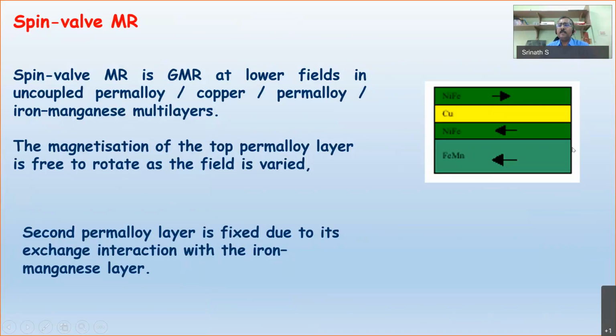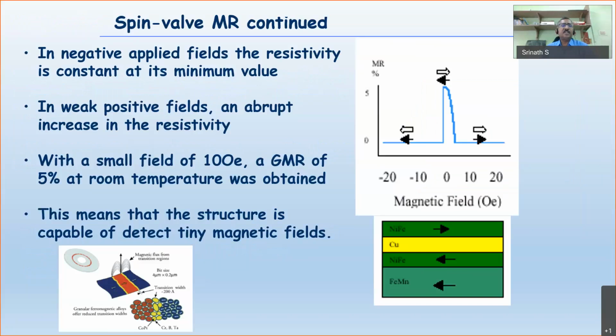So people have done, like, nickel iron and nickel iron. These are two ferromagnetic layers separated by a copper non-magnetic spacer layer. And one of the ferromagnetic layers is coupled with an antiferromagnet, iron manganese. So you can pin this layer, and the other can be tuned parallel or anti-parallel with respect to it just by applying a magnetic field, so that the resistance can change, the flow of electrons can change, and you can make it a spin valve. So this is a kind of structure you can do.